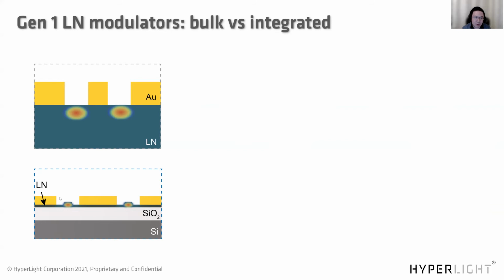And the approach thin film lithium-niobate takes is very similar to silicon on insulator platform. Instead of silicon on top, you replace that with lithium-niobate waveguide. And these waveguides are typically on the order of a micron or less. So it's a very close size to silicon. And the refractive index is about 2.2, which is very close to another popular platform, silicon nitride.